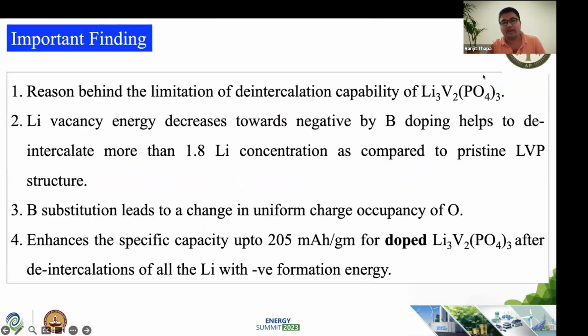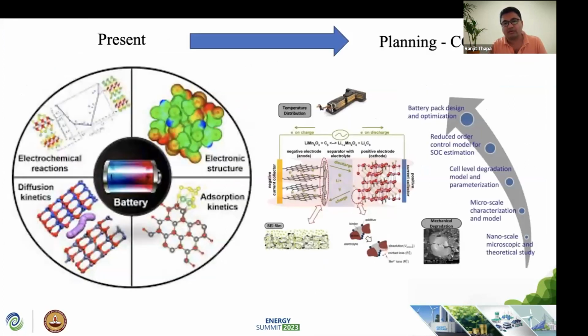An important finding I will say for the cathode is that lithium vacancy energy decreases towards negative with boron, which helps to have more lithium de-intercalation, and we can achieve around 205, which is theoretically, of course, a specific capacity. So this is the way we have done the work and addressed it.